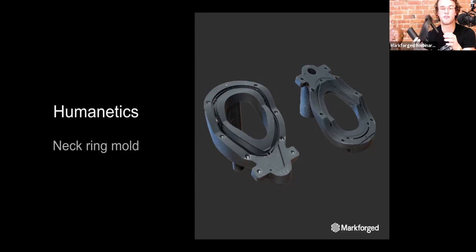And this mold ended up far outlasting the silicone mold and was 99% less expensive than if they were to machine it out of aluminum, because this would most likely have to be a multi-part mold if it were made out of aluminum.